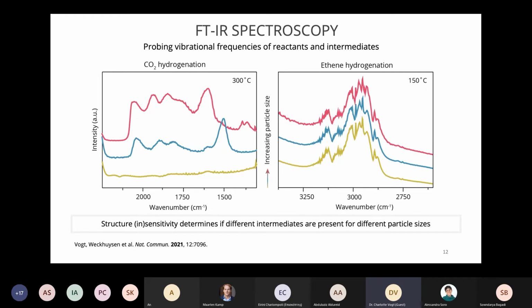So we're here checking what's on the surface, what's causing any different activity that we observed a couple of slides before. So here we see different nanoparticle sizes, small, medium, and large, increasing nanoparticle size, same here, small, medium, large. For the CO2 hydrogenation experiments, for the structure sensitive reaction, with activity changing for different nanoparticle sizes, we saw different reaction intermediates in IR. We saw, depending on the particle size, different peaks. And this was something that we'd already observed before. This was something that we used to explain the structure sensitivity effect in a previous publication. And now we took this structure insensitive one and see that for the different nanoparticle sizes, we see no change. We see no change in the observed reaction intermediates on the surface.